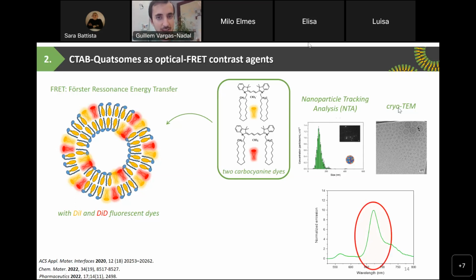And in this case, we recorded the emission of the second dye while we excite the first dye. So we excite the DiI and we read the emission of the DiD if there is FRET. In the emission graph, we can see the emission of the second dye, so we can see the emission of the DiD. So we have achieved FRET. We have the FRET phenomenon in our quatsomes, which is good because